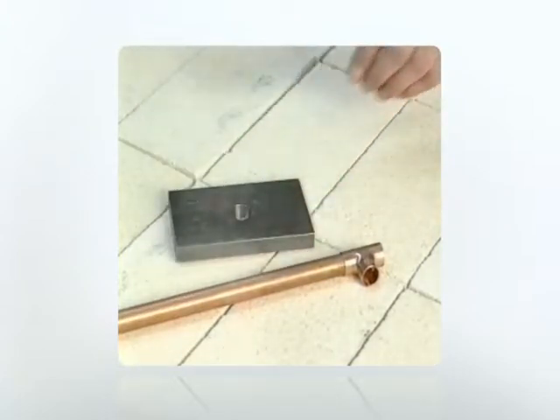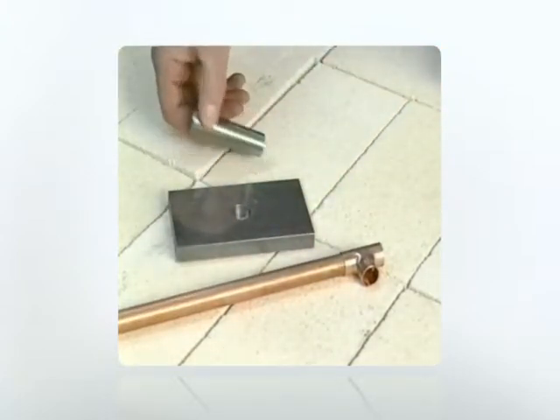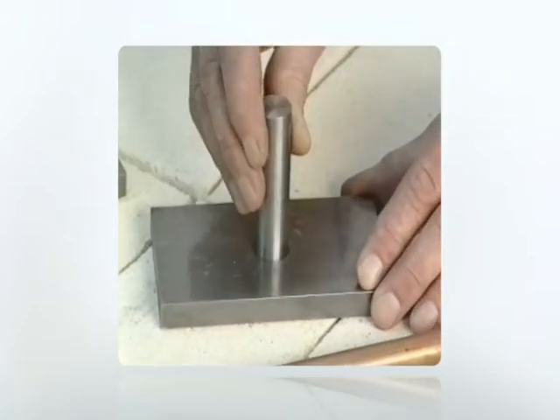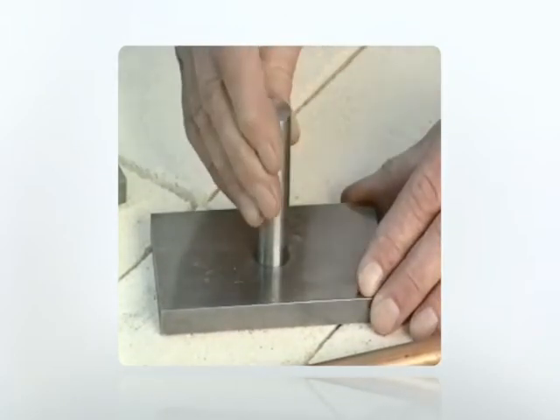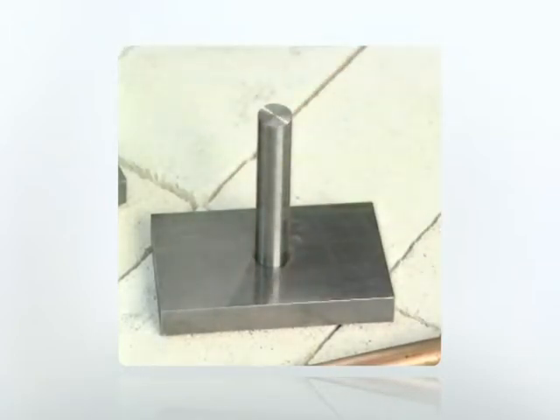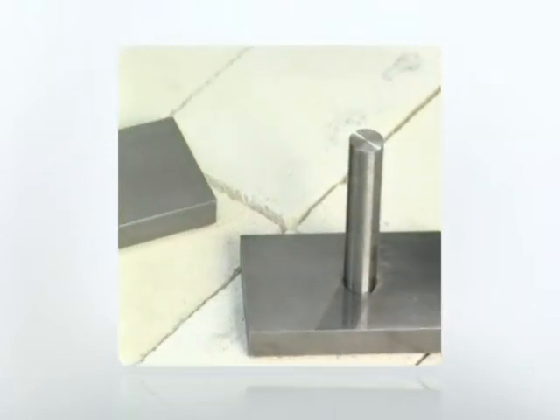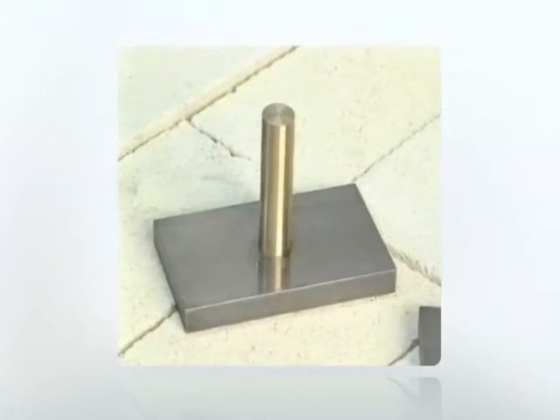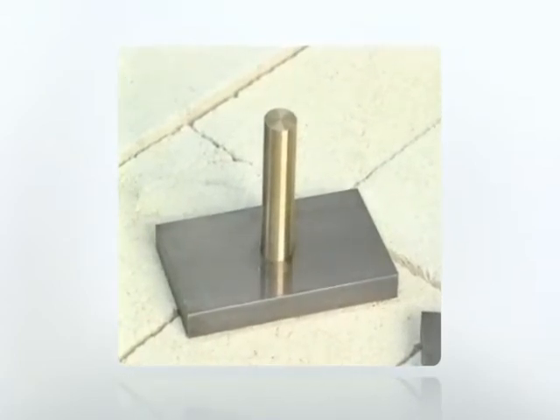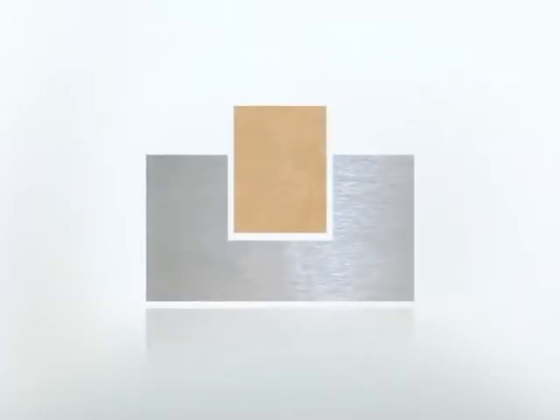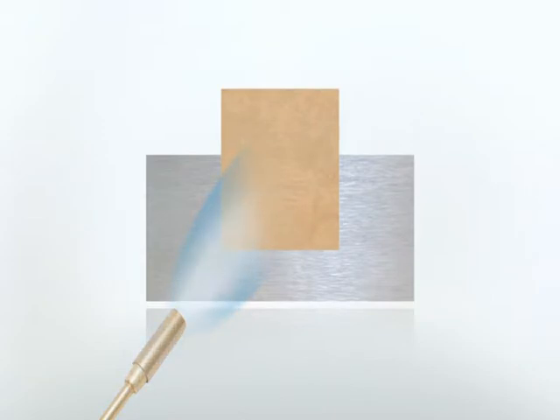When a metal is heated, it expands, and some metals expand at different rates to others. If two parts made of the same material are being joined, there's no problem. They expand together and the gap stays the same. But if dissimilar metals are being joined, such as a brass cylinder and a steel plate, allowance has to be made for differential expansion. The capillary gap at room temperature may be quite different by the time the joint reaches brazing temperature. If the joint is machined to provide a clearance of 0.05 at room temperature, by the time it's heated to brazing temperature, the gap will have completely disappeared due to the brass expanding faster than the steel.